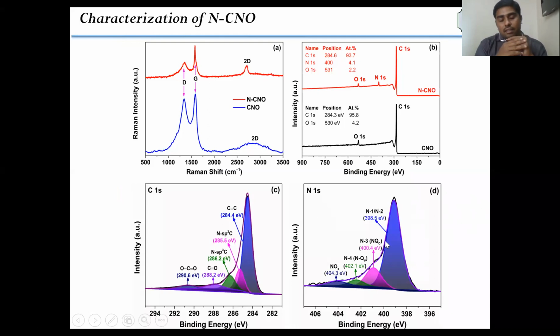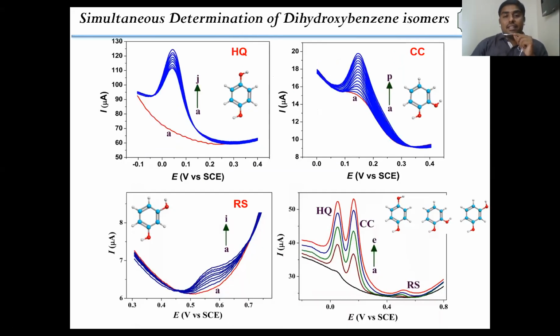So there is a nitrogen doping from the acetonitrile, and there's a formation of nitrogen doped carbon nano-onions, and the different N1s peaks for the different nitrogen moieties confirmed there is a nitrogen doping in the CNOs. So we utilized the carbon nano-onions fabricated electrode for the detection of dihydroxybenzene isomers, hydroquinone, catechol, resorcinol. Of course, the simultaneous determination of the dihydroxybenzene isomers. So this carbon nano-onions and nitrogen doped carbon nano-onion fabricated electrode can detect the dihydroxybenzene isomers simultaneously as well as in the real sample analysis also.